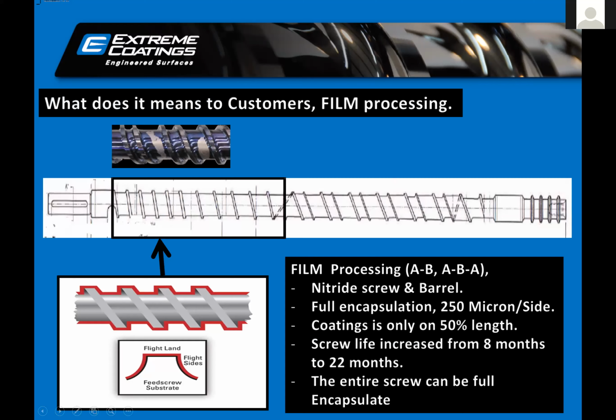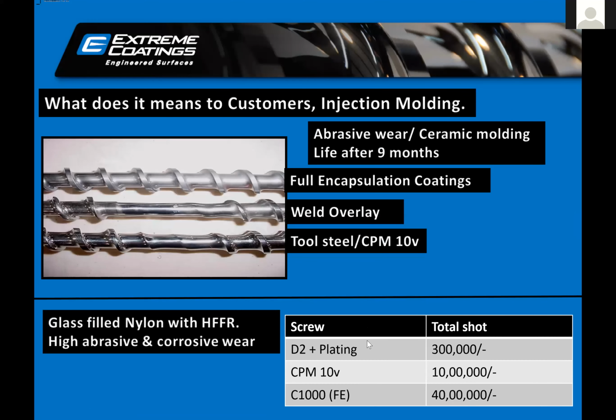If you are in injection molding, this is the case study compared to D2 plating. They were getting only 3 lakh shots. With CPM 10V, they got 10 lakh shots. With the coated screw, they got 40 lakh shots. So this is just a reference of how well it is performing.